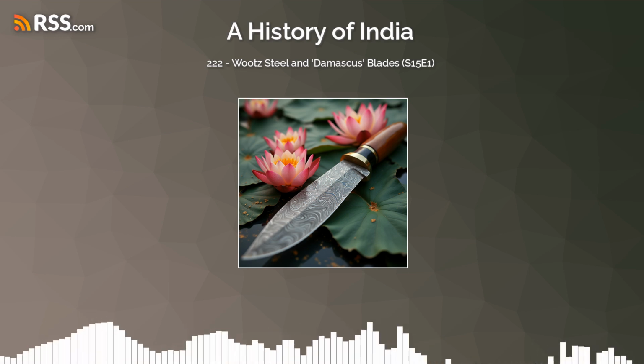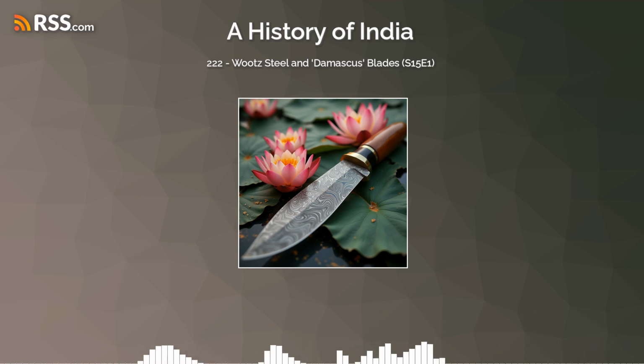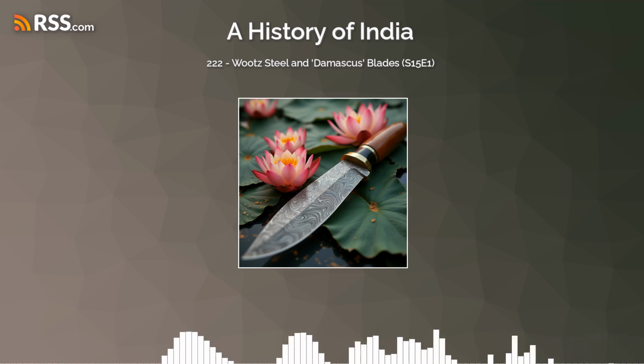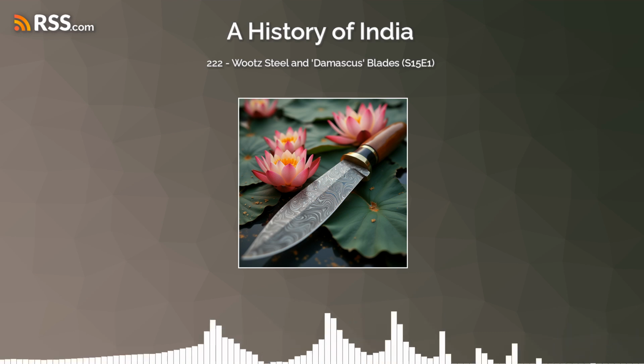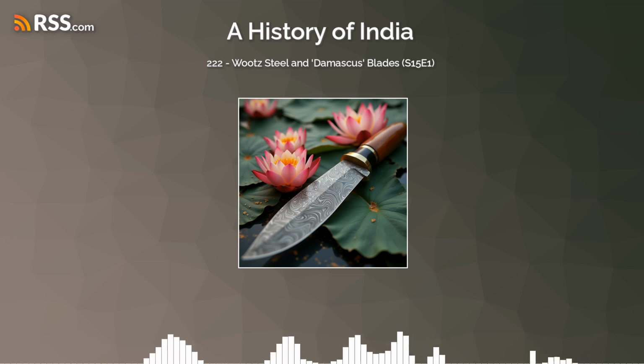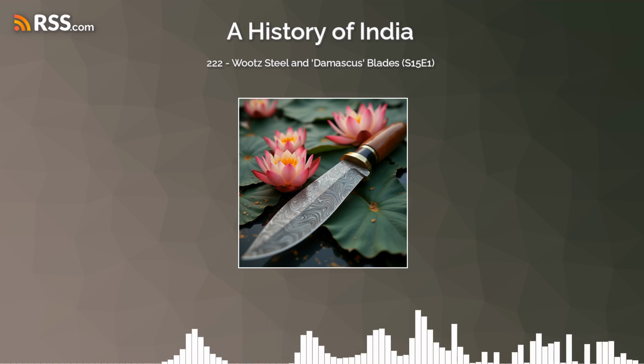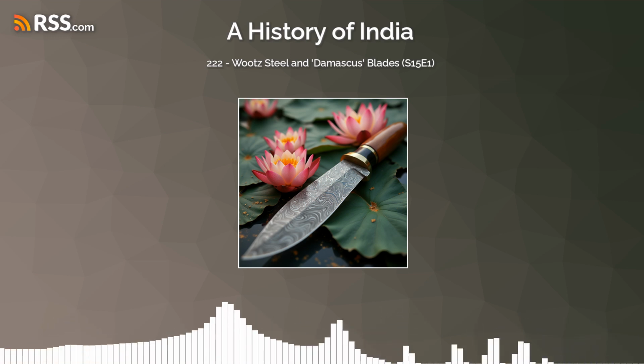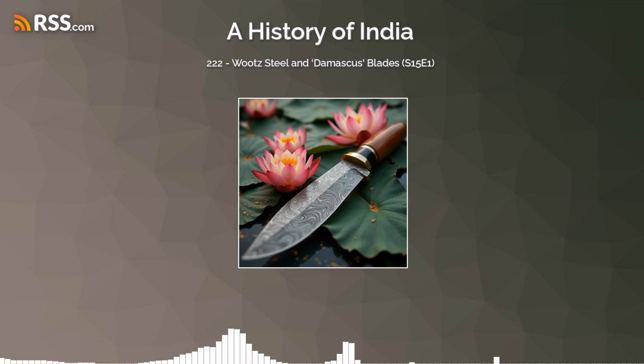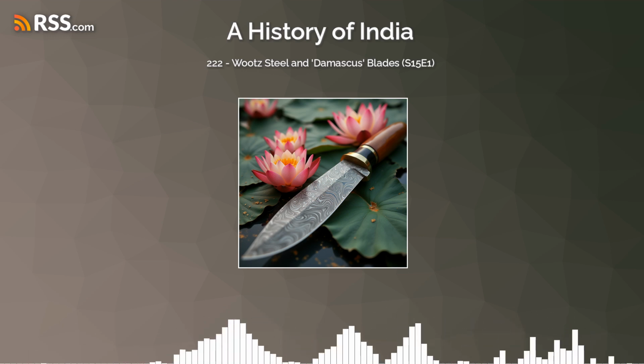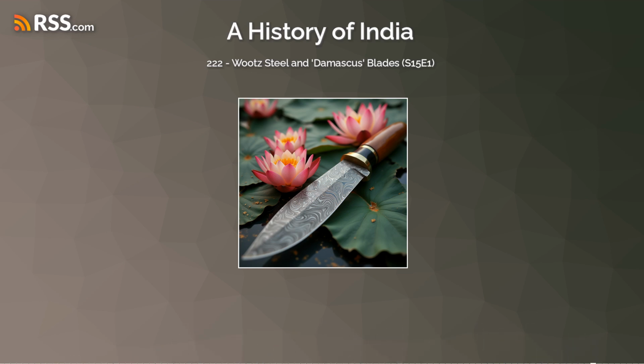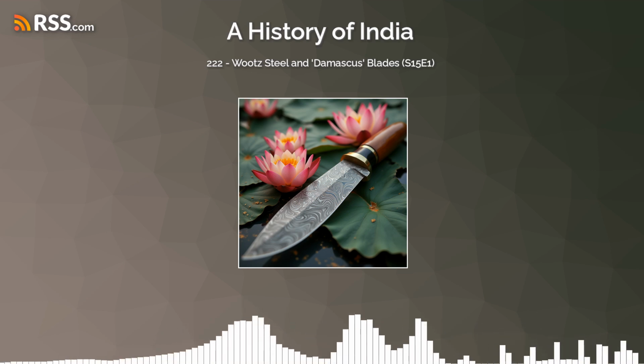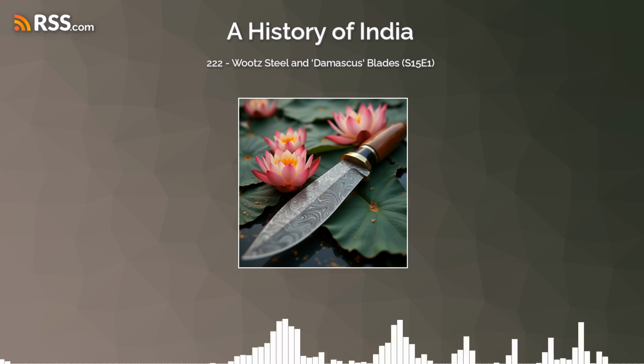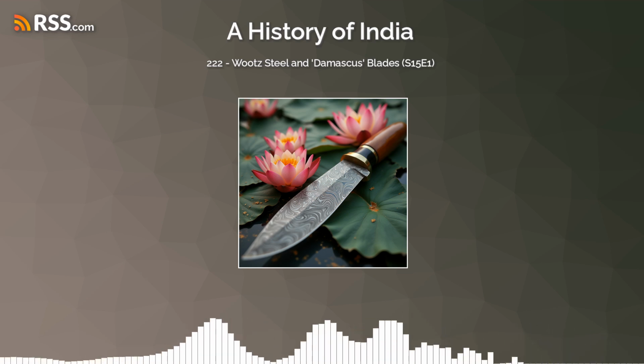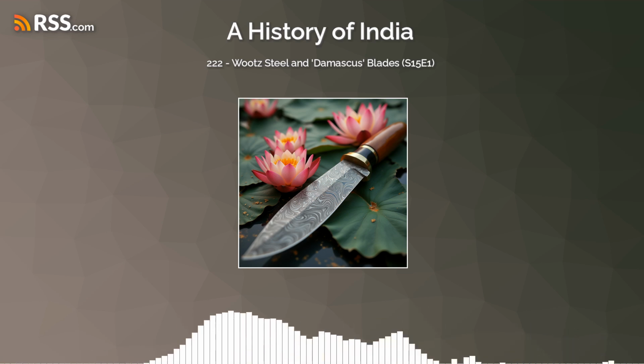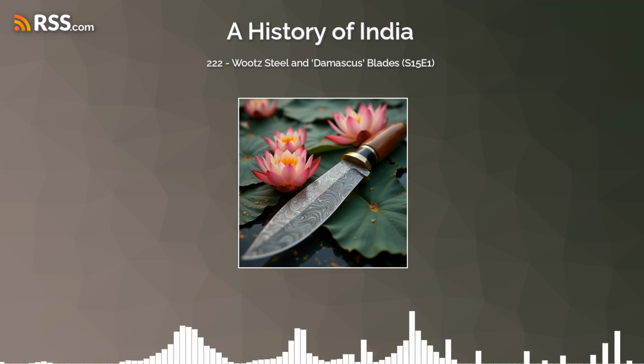And the legendary sharpness, did that come from the same process, this microstructure? Yes, very likely. Both the historical accounts and modern understanding point to something often called the micro-chainsaw effect. During that careful forging, those incredibly hard microscopic carbide particles of cementite could be preferentially aligned right along the blade's edge. Like tiny teeth. Exactly, like microscopic serrations. Imagine these tiny, incredibly hard, almost diamond-like particles embedded in the slightly softer steel matrix, forming a super fine cutting edge. When the blade was sharpened, these hard carbides would provide the actual cutting points. This structure would not only allow for incredible initial sharpness, but also contribute significantly to the blade's ability to hold that edge, its famous edge retention.